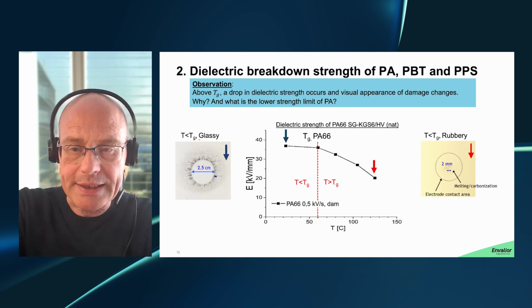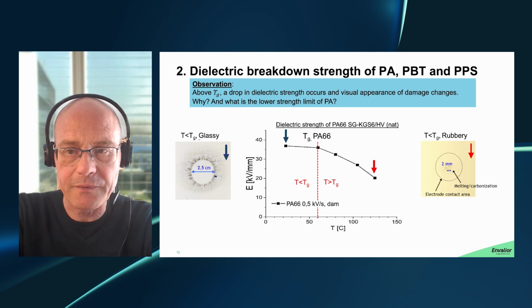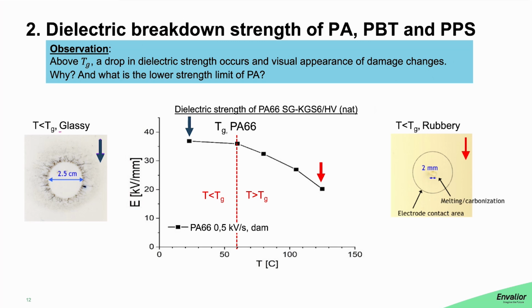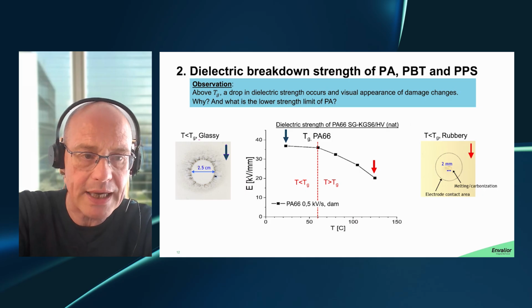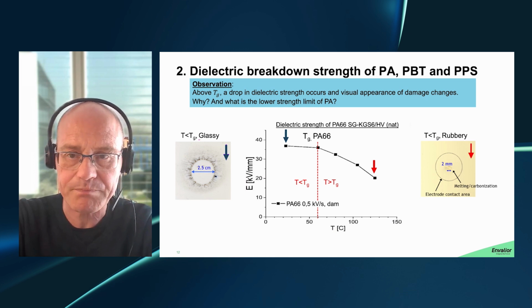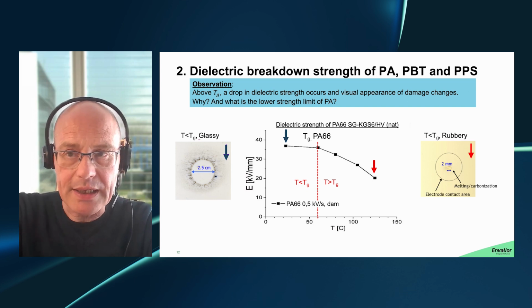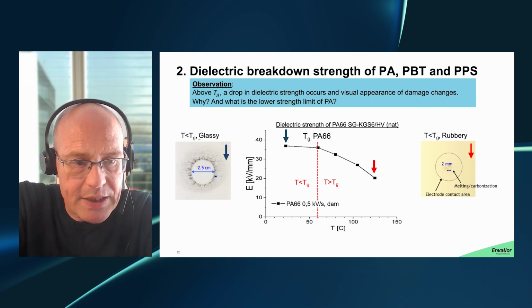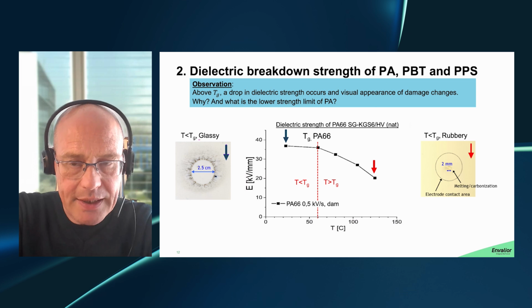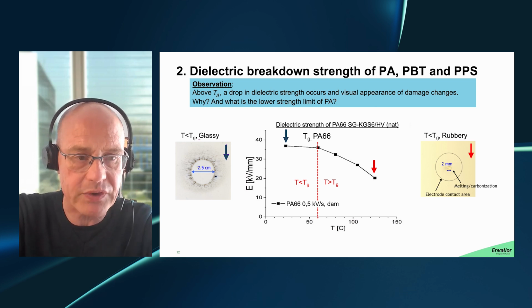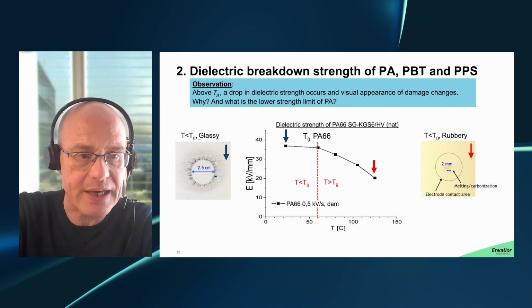Now, here you see the typical outcome in the center of the slide for polyamide 6,6. So you see breakdown voltage in kilovolts per millimeter displayed on the y-axis versus temperature. And what you see is that there's again a transition towards lower breakdown voltages at temperatures above the glass transition temperature. So when the amorphous phase of the material ends up in the rubbery state. Now, clearly, it's a question to ask, why does this occur? And I think it would also be very useful to know the lower limits of that strength, such that you can accommodate for the weakest strength in engineering applications.